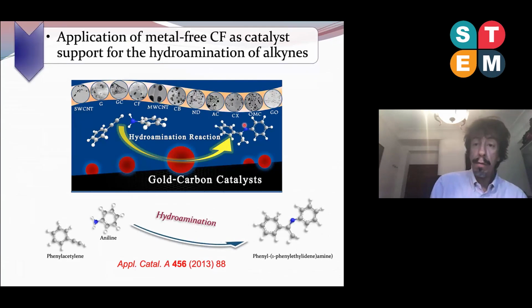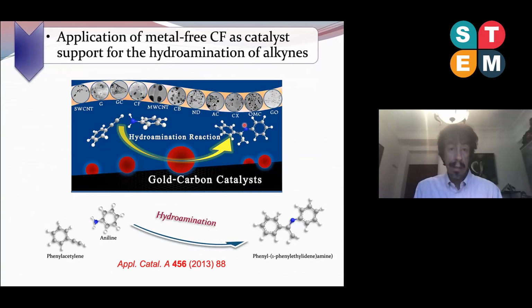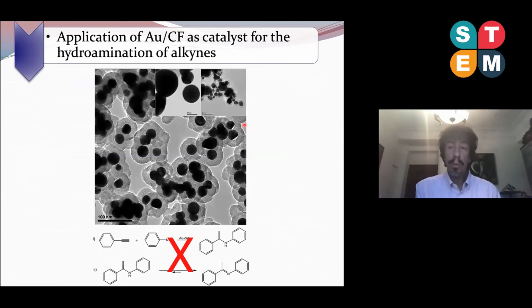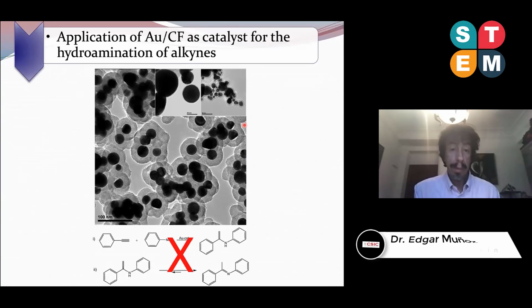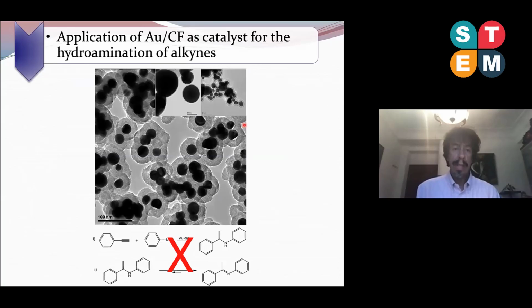We also studied our carbon foams as supports in catalysis, in particular for the phenylacetylene hydroamination with aniline that requires gold nanoparticle catalysts. We initially tried to do these catalysis experiments with our gold carbon foam materials, but our gold nanoparticles are all coated with carbon layers that prevent the interaction between the gold nanoparticles and the reactants. So for these materials, the catalysis does not work.